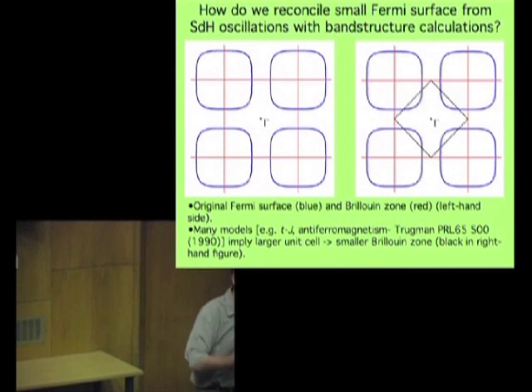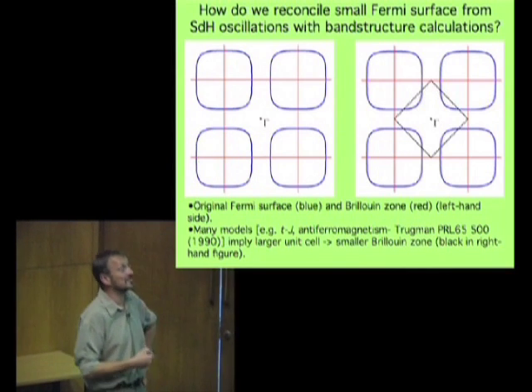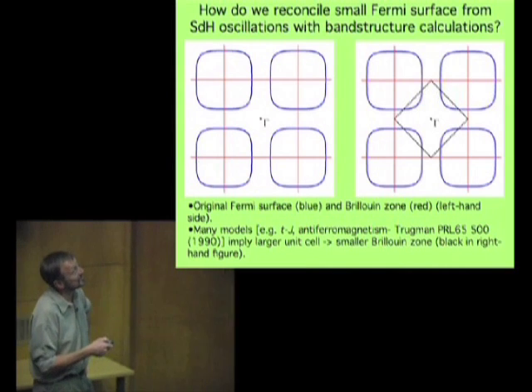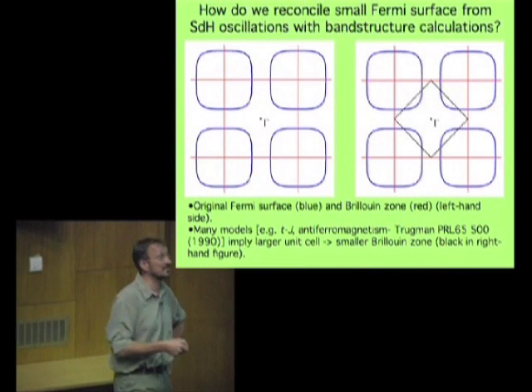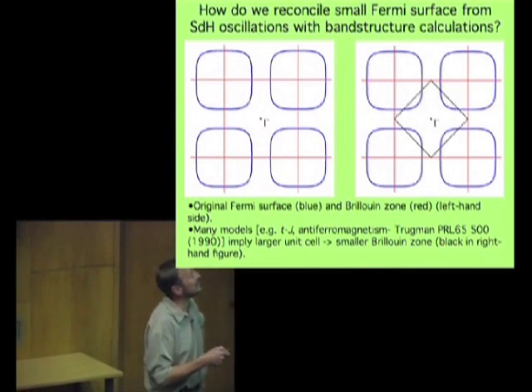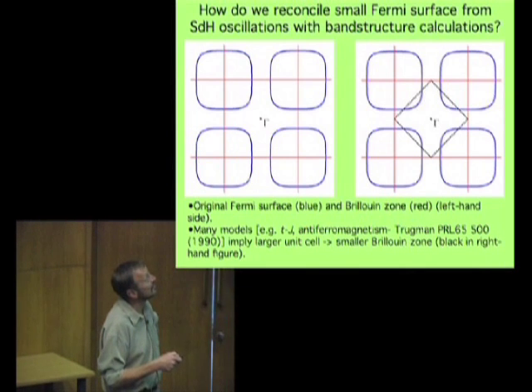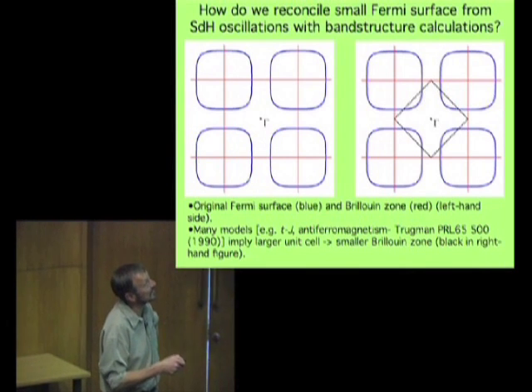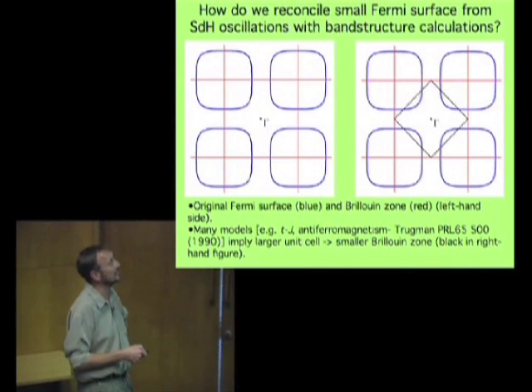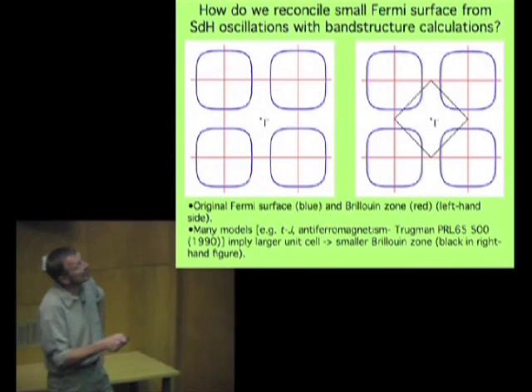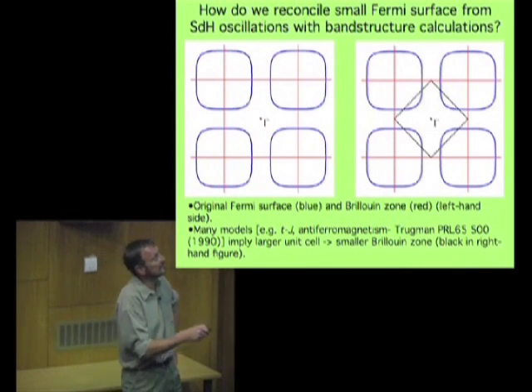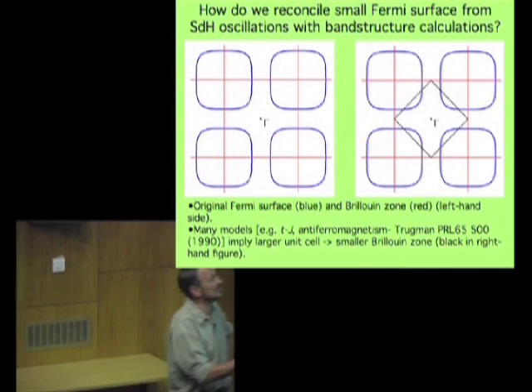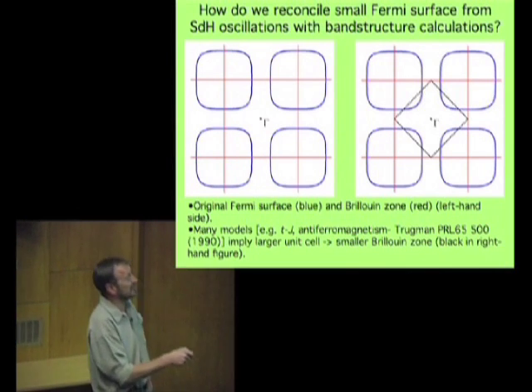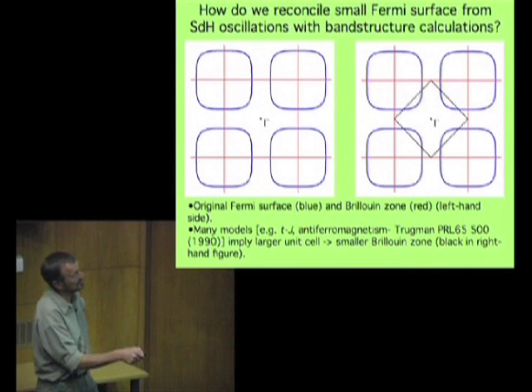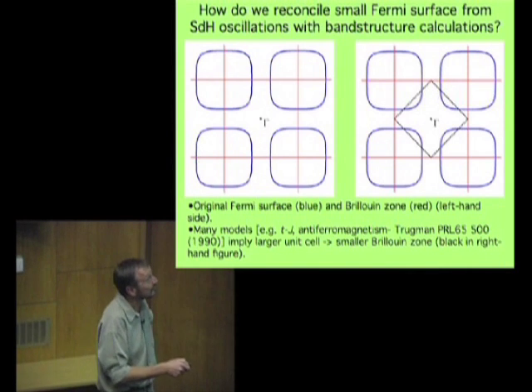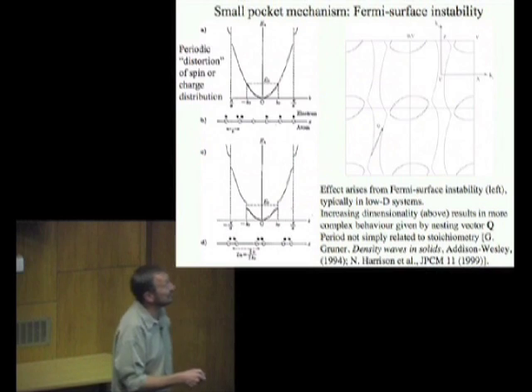Now, if you impose an additional periodicity in real space, what that does is it gives you an additional periodicity in K-space as well. So if you make the real space unit cell bigger, we have to make a smaller unit cell in K-space, like this black one here. And it turned out there are already a lot of proposals that this sort of Brillouin zone would actually exist in the cuprates because of things like incipient antiferromagnetism. These were made in the early days of the field. So where is this coming from?